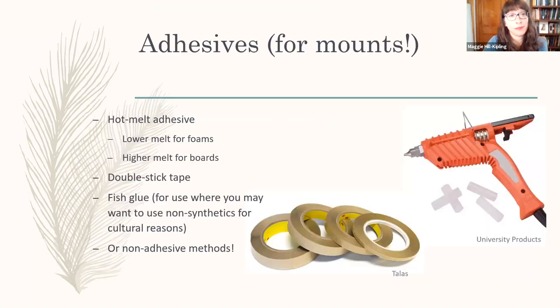And then adhesives. These are, again, just for mounts. These are not materials that we'd use on your objects. But hot melt adhesive, there are a couple of different ones available. There's a lower melt that's available for foams and a higher melt that's available for board. Double stick tape. And then we found, again, in some tribal consultations where we're wanting to use more natural materials, wheat starch paste or fish glue. Fish glue is nice. You can buy high-tack fish glue already made, and so that can be really convenient to use, and it dries a little more quickly than wheat starch paste. And then those non-adhesive methods, like I talked about with using the cotton tapes.